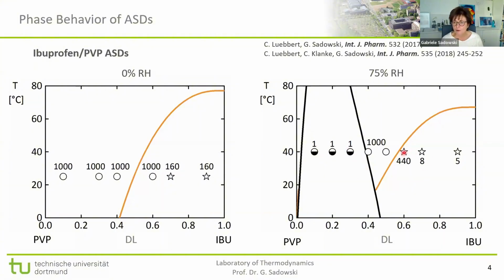The ones right off the solubility line did crystallize. Also, again, from the right to the left. That means the driving force for crystallization is highest for the ones farther away from the solubility line. This is after 5 days, this is after 8 days, and this is after 440. And the safe samples, so that neither crystallize nor phase separate, are indeed the ones in the middle, as predicted.